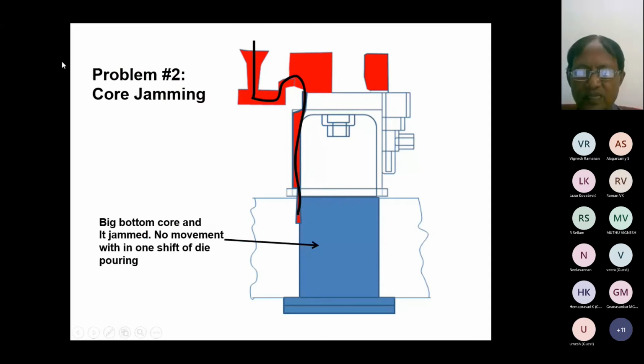Now, the gap is hardly about 0.3 mm per side. Unless we have 0.3 mm, the core will not go down. It's a very big core of 120 mm diameter, such a big core. A very long core of about, say, some 250 mm will be there, this height.